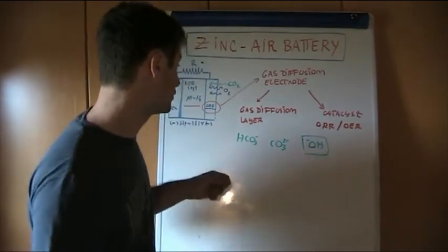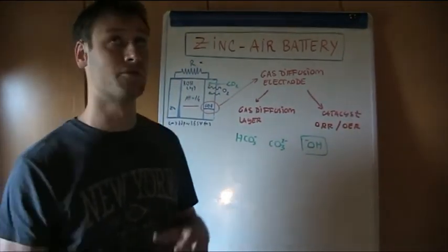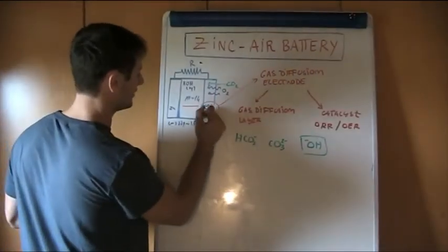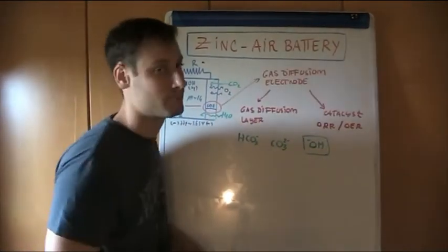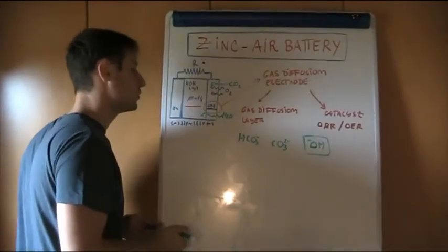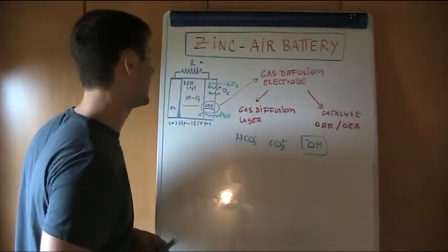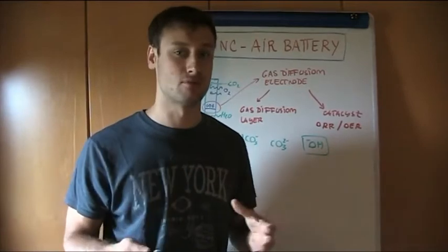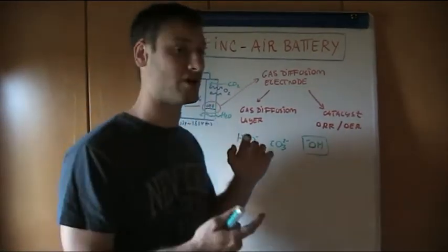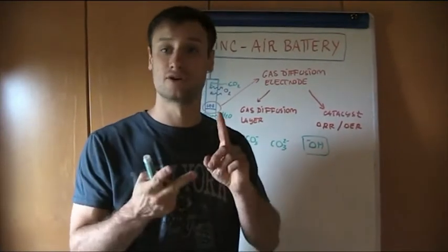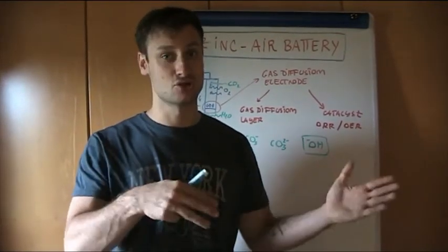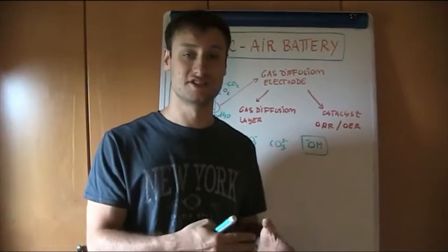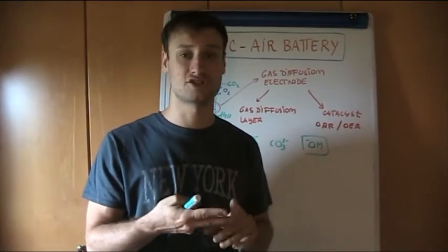Or even in humid situations, when maybe we are under rain or something similar, we can have the introduction of water inside. Obviously we have a Teflon binder trying to minimize this effect, but a certain small amount of water can still penetrate, and in this case we are diluting the electrolyte and again generating problems in terms of conductivity. So we have the problem of dilution, and the problem of concentration due to evaporation of the electrolyte: two opposite problems, movement of water from inside to outside and from outside to inside. In both cases we have a problem.